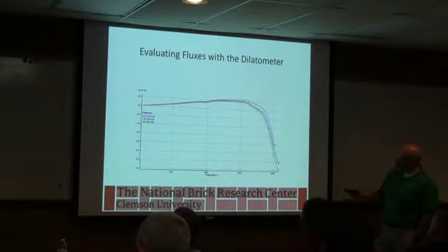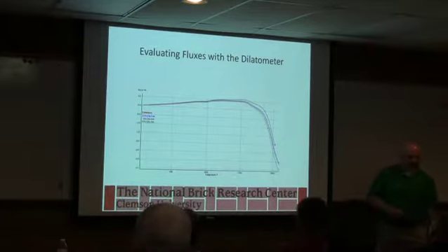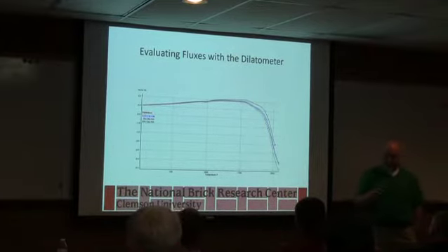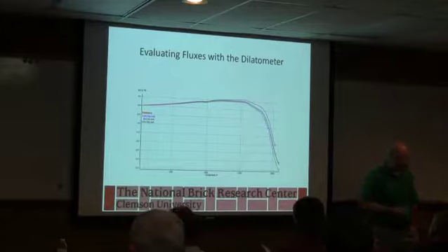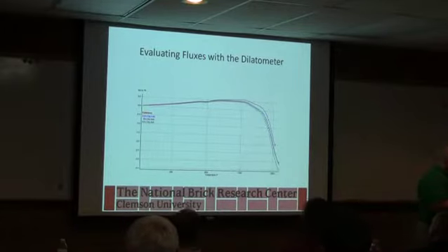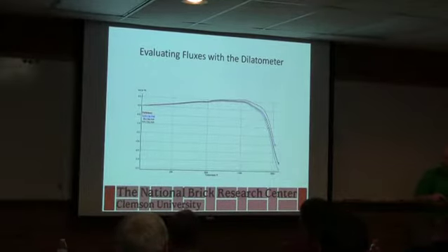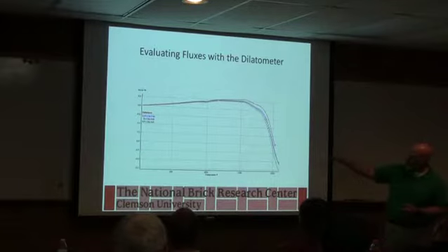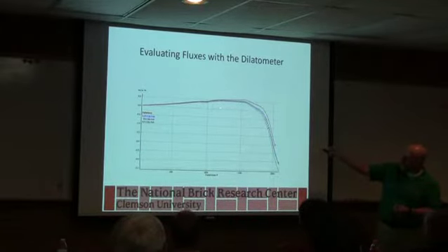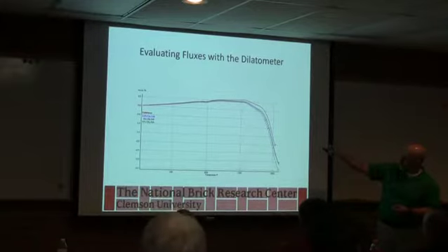Another tool you can use is called a dilatometer. Okay, you've got a dilatometer here, I believe. And basically what that does is you have a little piece of your material and you fire it and you monitor the dimensional change as you fire it. Okay, so when it goes through the quartz inversion, which we still haven't talked about, the material tends to grow a little bit. And so that's right in the range of the quartz inversion and the clay mineral decomposing.